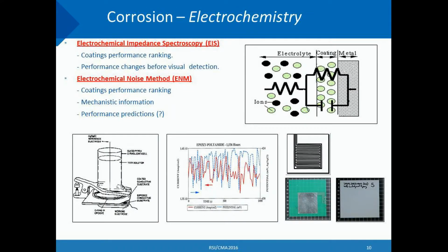Now, I'll just mention very quickly that since corrosion is an electrochemical process, it's very important to try and gather quantitative information on corrosion, and we do that in our labs principally by using two techniques: electrochemical impedance spectroscopy and electrochemical noise methodology. And the importance really is that both of these methods generate quantitative information about corrosion that's taking place under an intact coating. You can't see what's happening, but you can measure it by electrochemistry. And it can be done either on painted panels, or you can put probes under the surface of a paint and make measurements that way too.